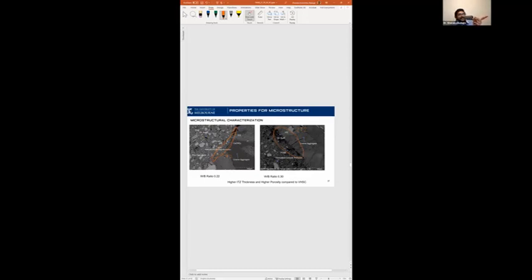So can you see the screen? I highlighted the ITZ there. The right side is the water cement ratio of 0.3, and the left one is 0.22. So you can see the porosity at 28 days is much higher in the right region. In all the specimens, it was like that. So there's a clear variation in that. I think the porosity is the main issue.